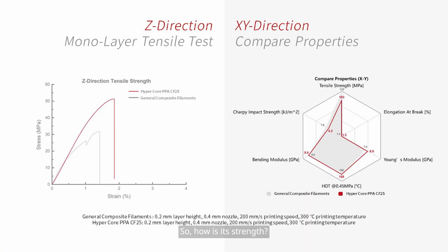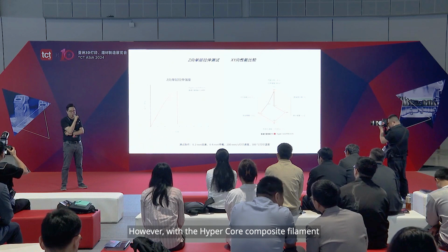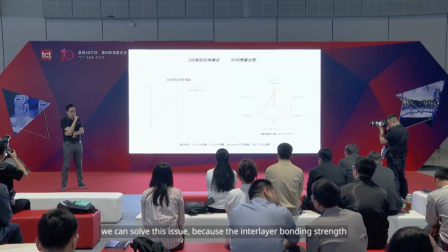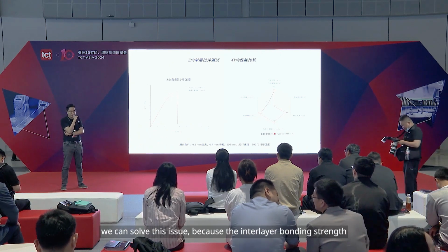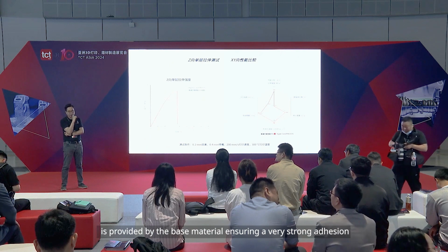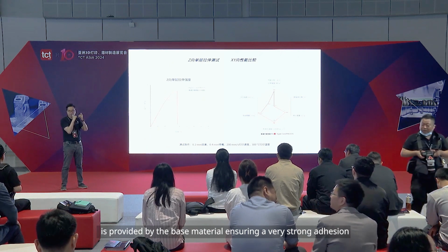So, how is its strength? As you can see, the biggest challenge when printing with short carbon fibers is in the Z-axis. The Z-axis stiffness and strength have greatly improved compared to the original. For carbon fiber, the challenge lies in the interlayer bonding strength, which is generally worse than PLA or ABS. However, with the HyperCore composite filament, we can solve this issue because the interlayer bonding strength is provided by the base material, ensuring a very strong adhesion.